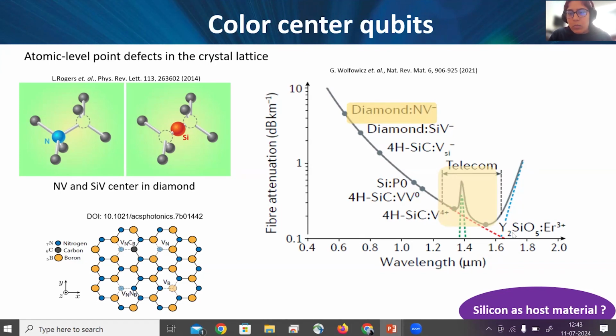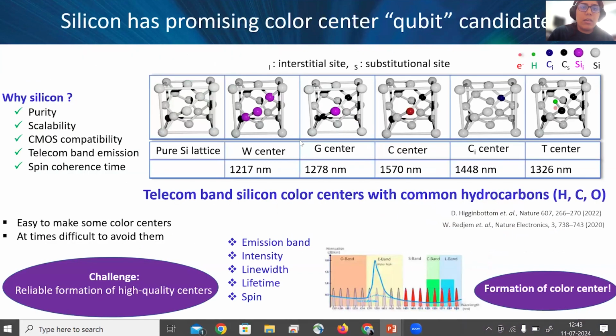Now the idea is which other material platforms we could explore which might have the color center emission in the telecom band. One desired material could be silicon, because silicon, as we know, is among the most pure materials we have. Scalability due to its CMOS compatibility is not a question. We have been using silicon for a couple of decades now, so we know the most about this material. And luckily, we already have a bunch of color centers in silicon emitting light in the telecommunication band. And inherently, the spin coherence time in silicon is also good. There can be a comparison also. It's not the best one, but it's still good enough to perform the fast operations that we would like to do.